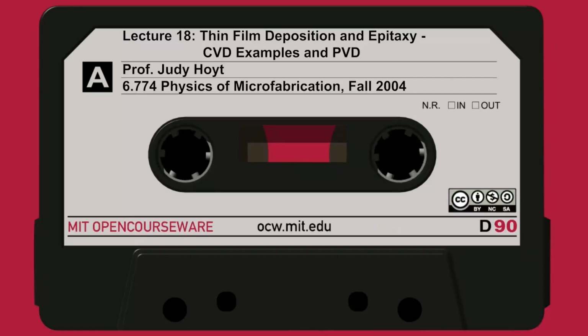It does more than oxide. It can deposit nitride, oxynitride, and other films. It's an RF plasma. It has an interesting thing. It has a multiple station processing sequence. It cycles each wafer through different deposition chambers or stations to get an averaging effect so that you get better uniformity. In any given tool, you'll often find if it has multiple stations, say it has 5 slots, slot 1 and slot 5 never have exactly the same dep rate. And it's always a problem. So you put 5 wafers in, wafer 1 and 5 come out differently. This is a very kind of brute force, obvious way to do it.